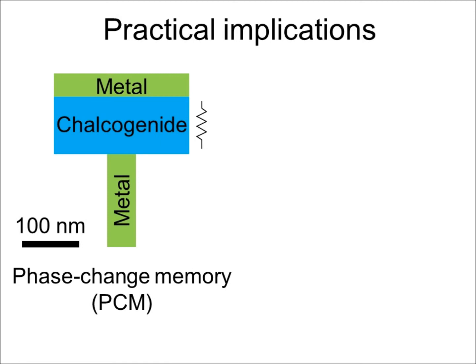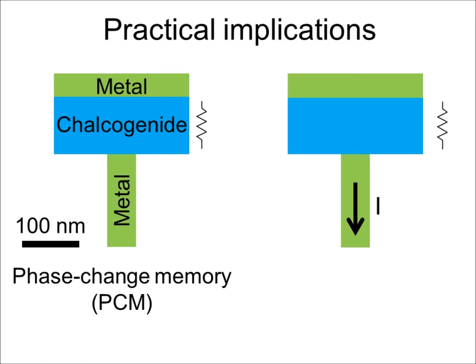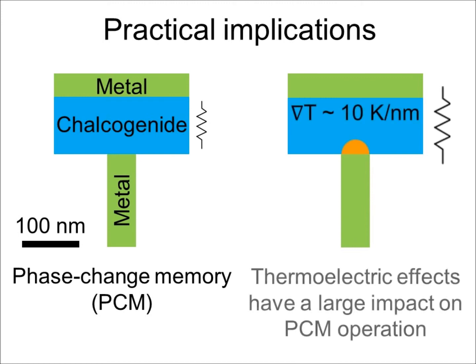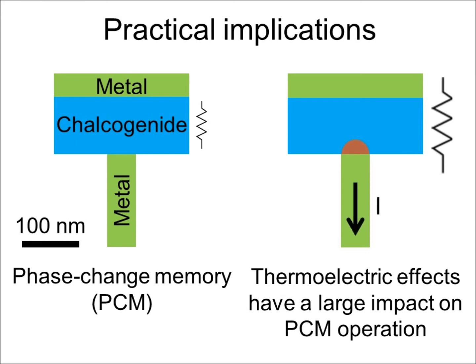When the chalcogenide material is in crystalline phase, it is electrically conductive. When a short-duration electrical pulse is applied across this device, a small volume of the chalcogenide material melts. Upon termination of the signal, the material then amorphizes, resulting in a larger electrical resistance. During this melting and amorphization process, the temperature gradient in the device can be as large as 10 Kelvin per nanometer, which leads to strong thermoelectric effects. The initial crystalline state is achieved by self-heating the amorphized volume with a lower amplitude and longer duration electrical signal.